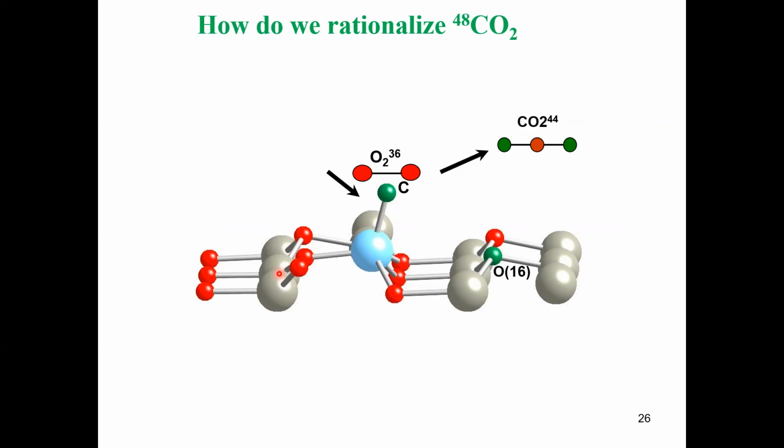So what am I trying to say? It is not enough for a computational scientist to just say, I have this result. You should have the maturity to work with experimentalists to propose the kind of experiments. In this case, we proposed an experiment with the O2 molecule where both oxygens are isotopic, O18 as opposed to O16. These are isotopically labeled, so we can detect what kind of O2 from mass spectrometry. We can detect different CO2 which have different molecular weight,